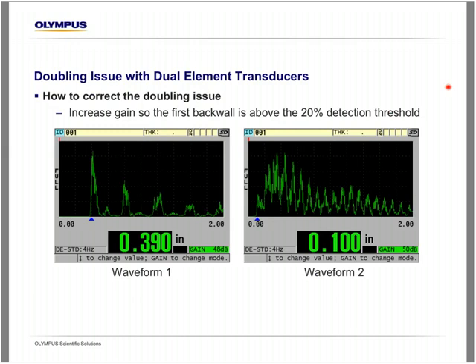So how would you correct this? You'd increase gain. You basically increase the gain enough so that that first signal is above the 20% detection threshold. So you'll see now on the left in waveform 1, everything's still good, but on the right, waveform 2, that first signal is above 20% and is now being detected.